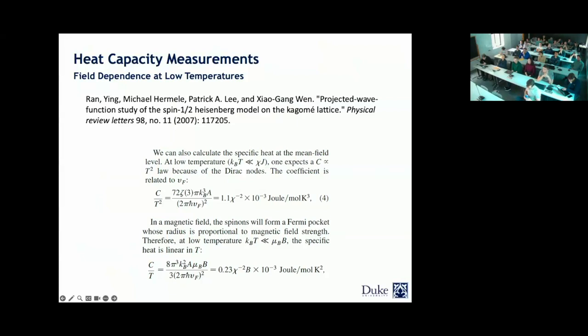They also looked at it as a function of magnetic field. Again, at the range of very low temperatures and very low, actually, to be honest, this turns out to be very low as well, at the low temperatures and low magnetic fields, because this is going to be the limit where the Dirac physics is valid. In this case, they said that the C over T is going to look something like this, which is linear with B, meaning that if you plot C over T at different B values or different magnetic fields, it starts to go up as a function of that.